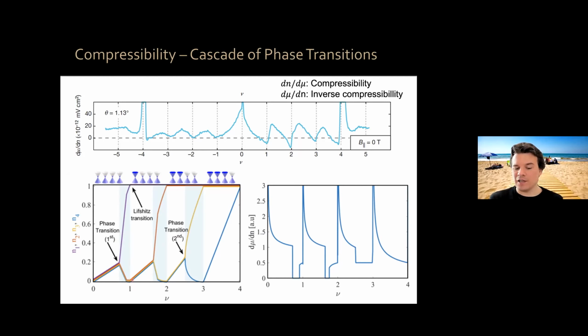You now fill the other 3 remaining flavors, close to 2. The system spontaneously polarizes into 2 of these flavors fully occupied, the other 2 fully empty, and you do this again. That thing is called a cascade of phase transitions. And it can be understood as, due to Coulomb interactions, it is energetically favorable for the system to polarize into 1 flavor and empty the other flavors. And that gives you this sawtooth behavior theoretically. So that's all I want you to know, for now.